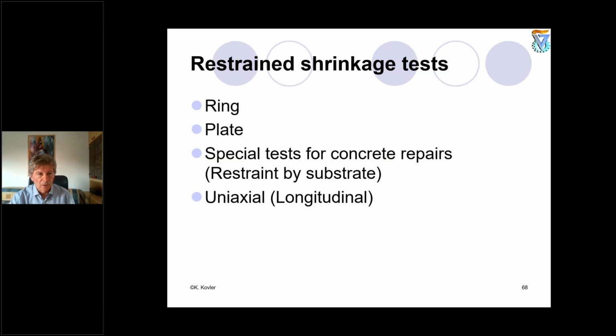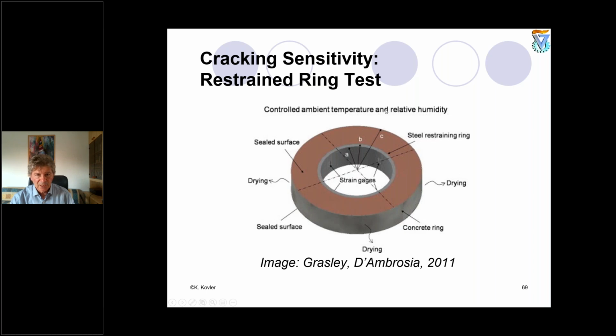And for characterizing the restraint shrinkage of the specimens, the authors developed different kinds of techniques: ring-based tests, plate tests, special tests for repairs, restraint by substrate, and uniaxial, for example, longitudinal or uniaxial. This is a very common and very popular test for restraint shrinkage. It's called the restraint ring test.